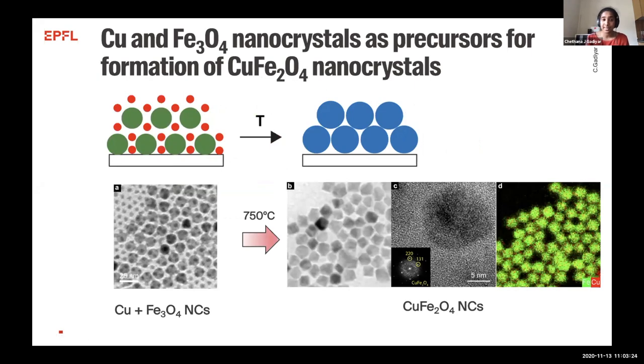So what we did is we reacted these two nanocrystals, and here what I show is an identical location TEM image. So we start with copper and iron oxide nanocrystals as a film. And when we anneal this sample to 750 degrees Celsius, actually what happens is all this copper starts reacting with the iron oxide. In panel A, the small spheres are all copper nanocrystals, and the big spheres are all iron oxide nanocrystals. And what we saw from this identical location image is that the copper iron oxides that are formed actually have a size which is very close to that of the iron oxide that we start with.